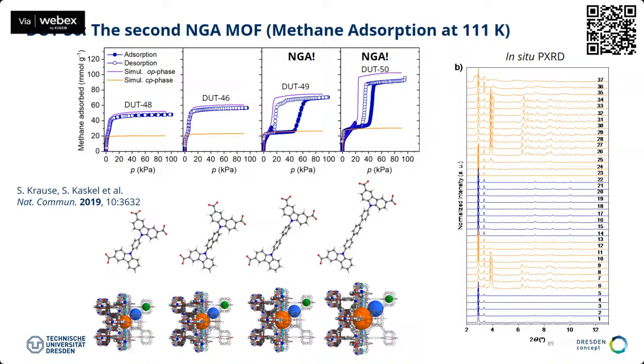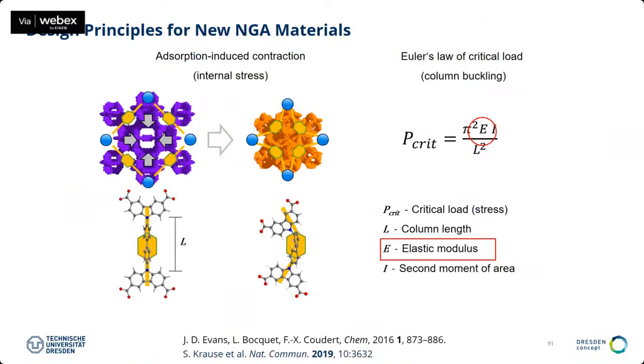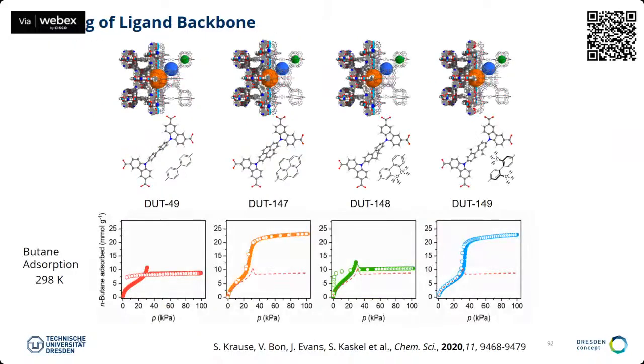Up from a certain length, you will observe these breathing phenomena, these structural transformations, and then also negative gas adsorption. And then you can also follow this with in situ PXRD techniques. You can also tailor the elastic modulus, in other words, the thickness of the column. So we also did this here. We made these pyrene-substituted linkers, also DUT-149, for example. This is still unpublished, but probably will come out very soon.